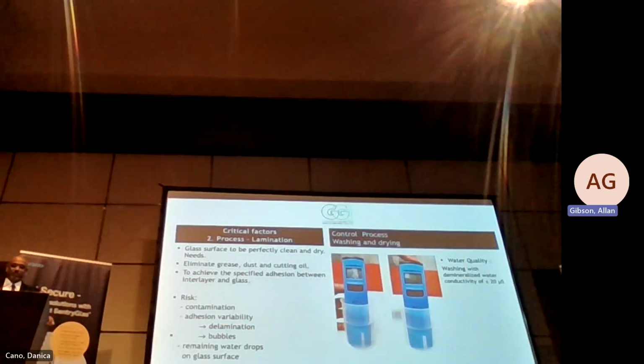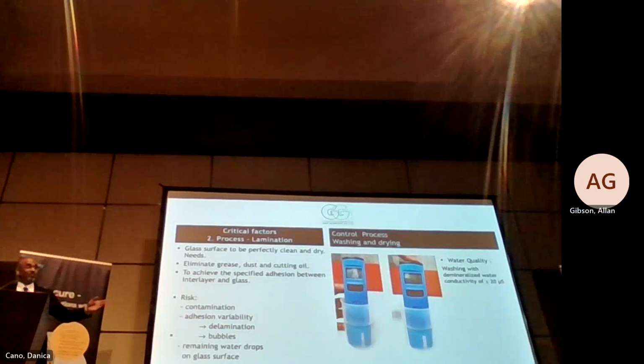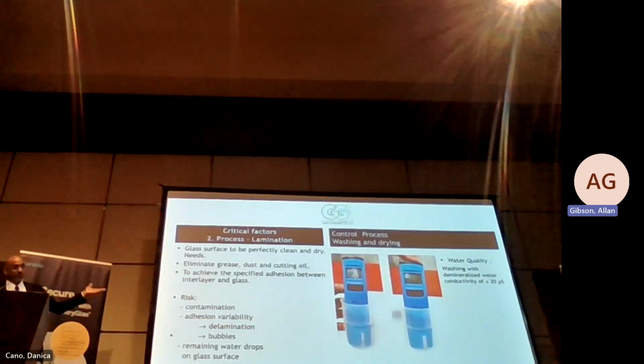We spoke about washing. The water that we drink has a conductivity of nearly 670 microsiemens. The water that we use in washing the laminate is only 16 to 20 microsiemens. So you need to be careful about who is processing your glass and how it is being processed. The conductivity of water also affects your lamination. It will cause variability in adhesion, and that will cause delaminations later on, and bubbles.